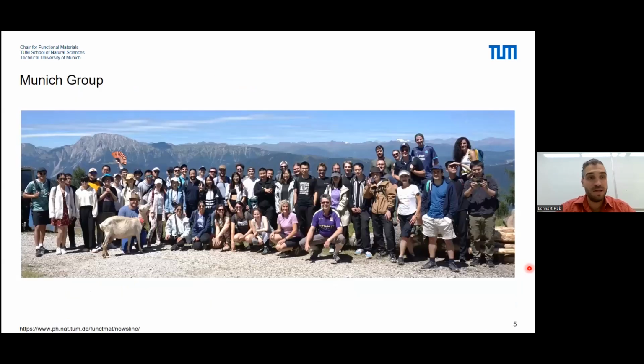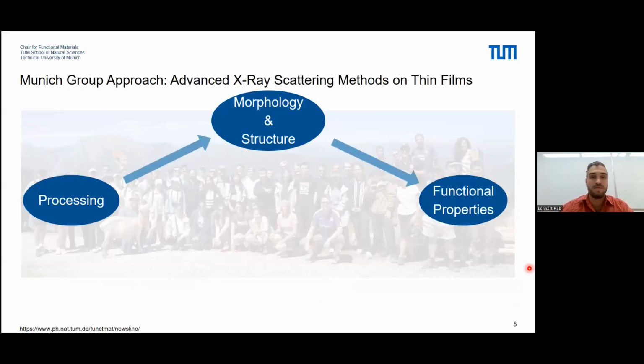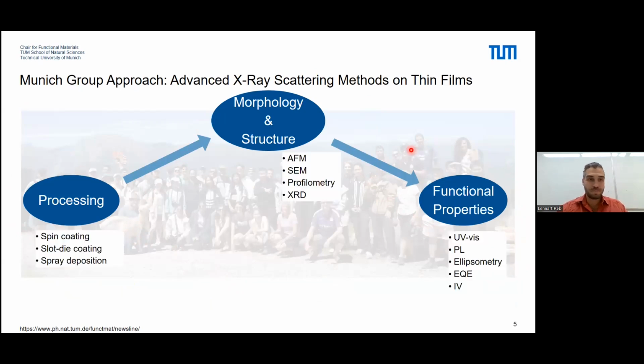Okay, some words about the expertise of our group. I'm going to show you our group approach, which is advanced X-ray scattering methods on thin films. And for this, I want to introduce the triangle, which ranges from processing that defines morphology and structure, which in turn defines also functional properties. So this is a list of methods we're usually using in the group, and all these methods I've also used during the work of my PhD. So the processing can be done by lab scale spin coating, but we also have a slot die coater, and we can do spray deposition. Classical morphology and structure analysis techniques include, but are not limited to AFM, SEM, profilometry, and XRD measurements.